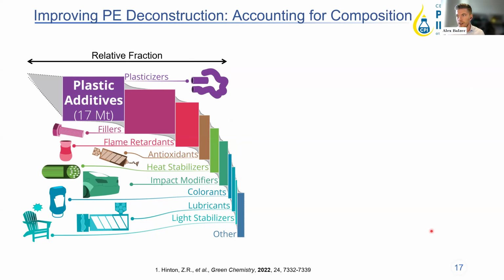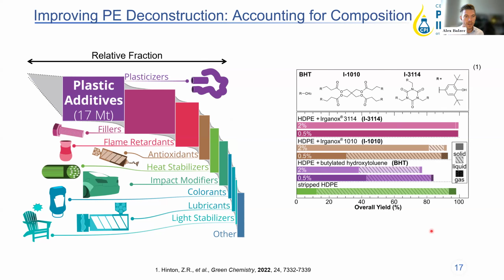How do all these additives that are in these plastics affect the deconstruction? And so we looked at a few different antioxidants during this hydrocracking process. And what we noticed is that in the presence of no antioxidants, this stripped high density polyethylene, in this case, not low density, gives the greatest liquid yield on a carbon mole basis, which is really the high value targeted product in our hydrocracking process, which is what we want. But when we start adding antioxidants, depending on their chemical structure, it poisons the catalyst surface, deactivates the catalyst. And so we can start to understand what sort of antioxidants, what sort of fillers or plastic additives you may have in your feed that affects your process.